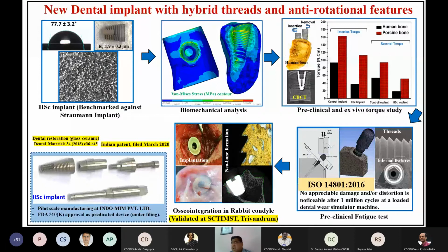Subsequently, we have done a dynamic wear study using a dental wear simulator, and then we have implanted these implants in the rabbit condyle, and this shows the micro CT of the implant after implantation, and then the neobone formation in histology images. We are currently taking this to pilot scale manufacturing at INDO-MIM Pvt Ltd. This is one of the works at NIT Surathkal with Somen Mondal's group. So,